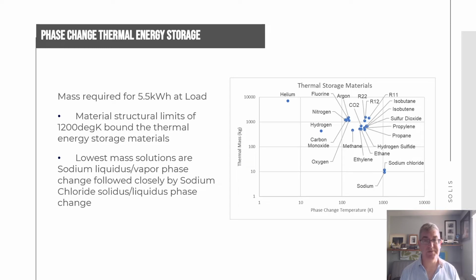When looking for energy storage materials for thermodynamic cycles, you're looking for solutions that have a temperature range within the material limits that you're able to use. Using Inconel as our primary structural material, we can get decent strength up to about 1200 Kelvin. And you can see the choices of working fluids, energy storage fluids in this lower right. And you can see that the lowest mass solution revolves around the sodium and sodium chloride solution, which respectively are the liquid to gaseous transition and the solid to liquid transition. They're almost exactly the same, with a total mass for the energy storage of around 9 kilograms for a 5.5 kilowatt hour energy storage.